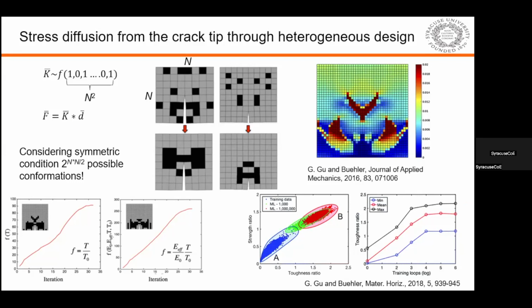That can dissipate the stress. Later, once there were machine learning methods, the lattice number could increase to around 100. Then you can use a small amount of training data obtained from finite element simulations to train the machine learning model and directly predict and categorize the best conformation that gives you higher strength. You can also change the objective function to be either just the toughness or a combination of toughness and the stiffness of the material.